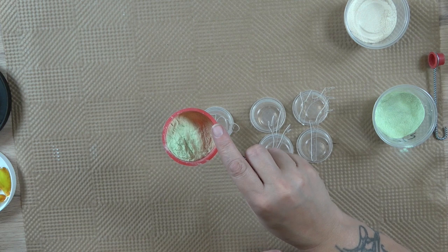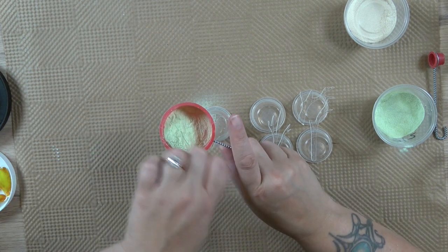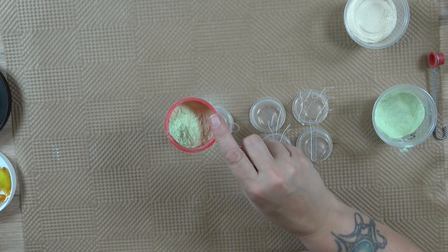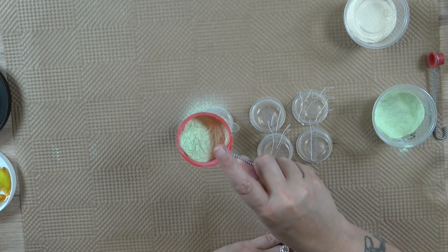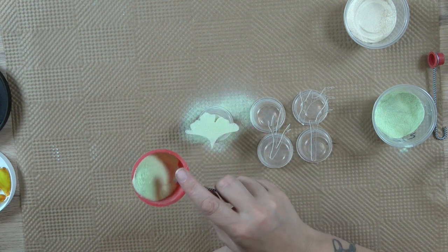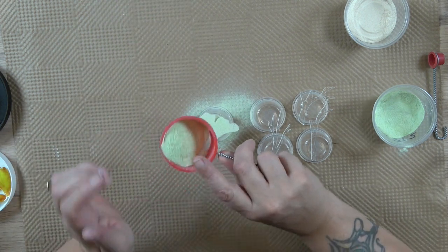All right, 2 inches from the top, masks are on, and you're going to just tap it with your finger. Don't vibrate the handle like you've seen. That's how these are supposed to be used. Too much powder is going to come out. I want you to tap and move on and pay attention. That's 1 layer. This is the most important part of the process, so we have an even surface to build that powder paste on, okay?